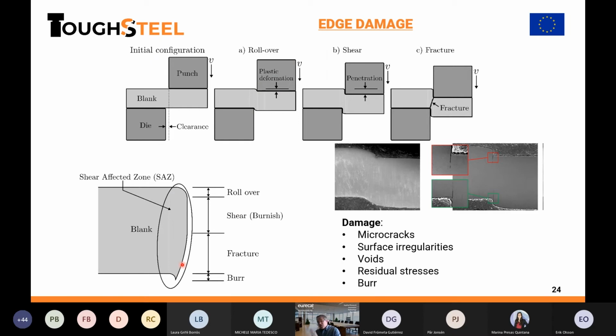If you compare a damaged edge and the non-damaged edge, we see the difference in the edge cracking appearance. So where is this edge damage coming from? It comes from the forming process. This is a profile of a cut edge. This is the blank. This is where the punch comes in and the punch comes out. We have a rollover area first, a shear area, and a fracture in the burr.